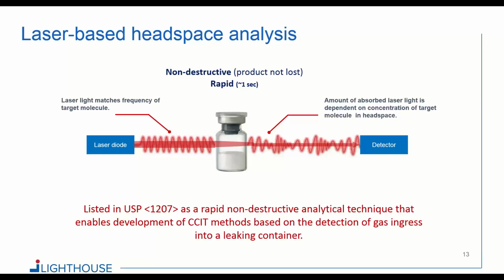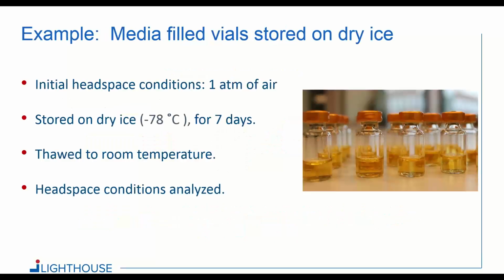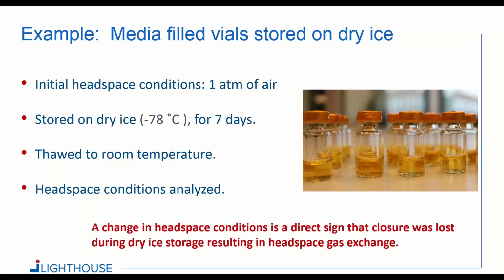So just how this actually works in practice, and to give you some data here, here's an example of media-filled vials that were stored on dry ice. Again, the initial headspace conditions were 1 atmosphere of air. They were stored on dry ice for 7 days, taken out and thawed to room temperature, and then the headspace conditions were analyzed. So any change in these headspace conditions would be a direct sign that closure was lost in the storage.